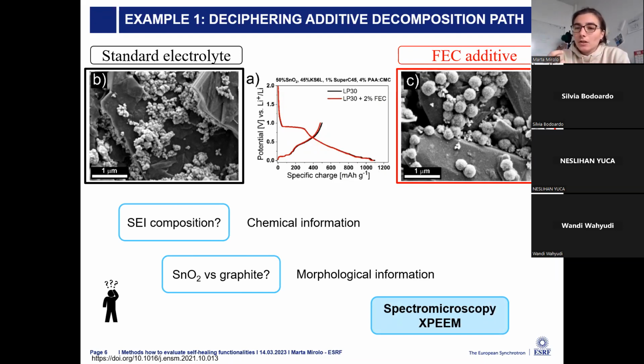Is it the fact that we are using a composite electrode? So do we have differences in the SEI formation between tin oxide and graphite? So what's happening? Why do we get improved electrochemical performances? So we need to have both chemical and morphological information, because we also want to distinguish between tin oxide and graphite SEI formation. So for this study, we decided to use spectromicroscopy, which combines chemical and morphological information.